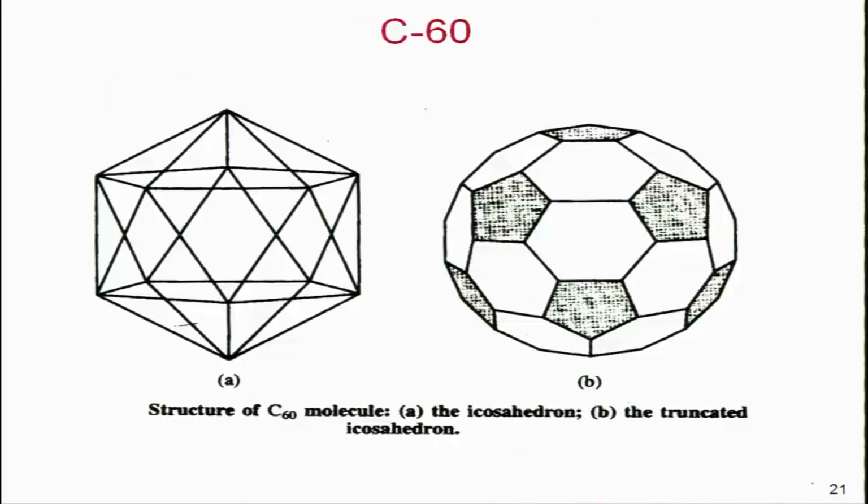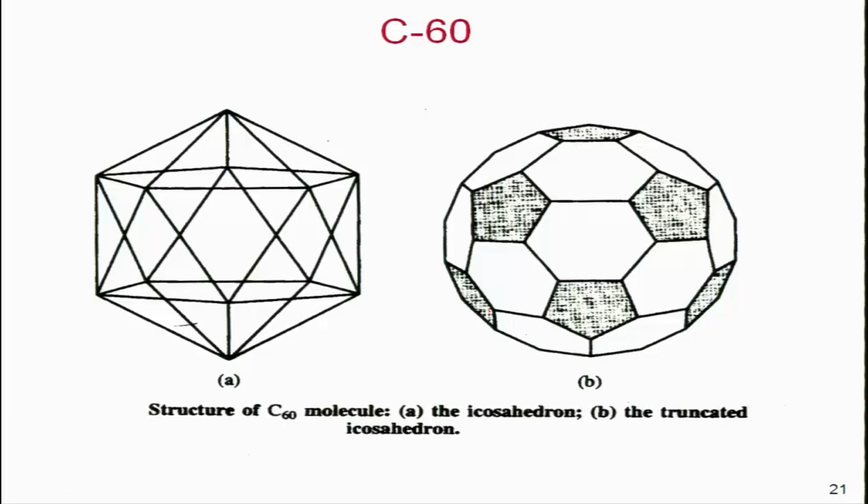diamond. This is the structure of another covalent material called C60, which is the Fullerene buckyball kind of structure. So it has a football shaped structure where carbon atoms are arranged in such a fashion so that you see these hexagons and pentagons arranged. So you can see that if you only had pentagons, it will not make a structure, but if you put pentagons separated by hexagons, then it can make a ball kind of structure. So this is the C60 molecule which is called Fullerene, and this is again a covalently bonded material. You can see that each atom has three neighbors here, sp2 hybridized structure.